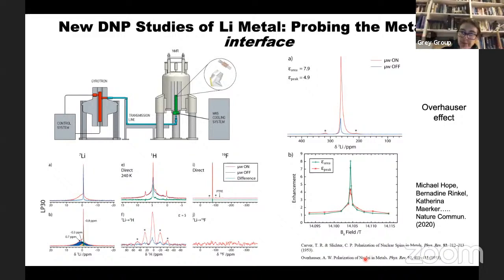So those of you who've done some band structure know that at the Fermi level of a metal, you have unpaired electrons and they have spins, and you can use those spins to polarize the lithium metal. And so Overhauser predicted this in '53, and Charlie Slichter actually demonstrated it the same year. And so the first measurement of dynamic nuclear polarization was on lithium metal.